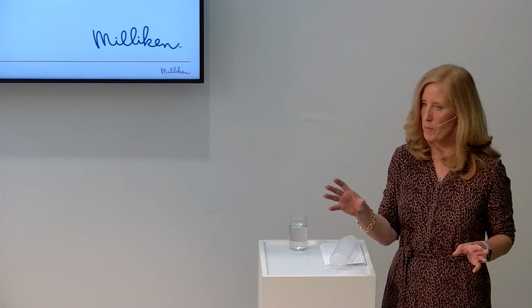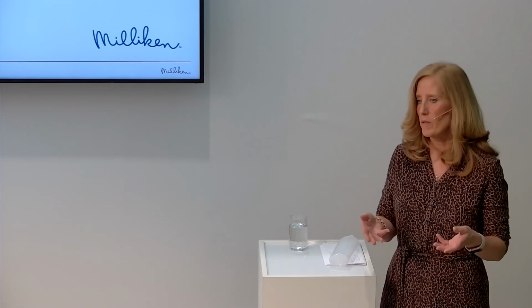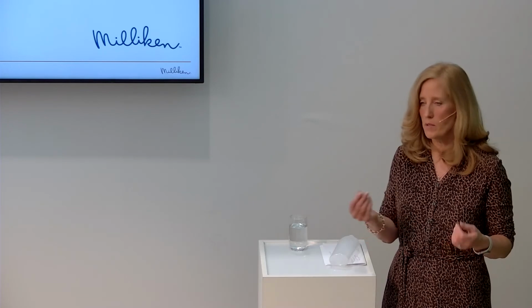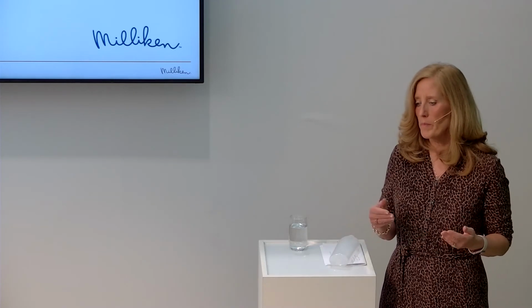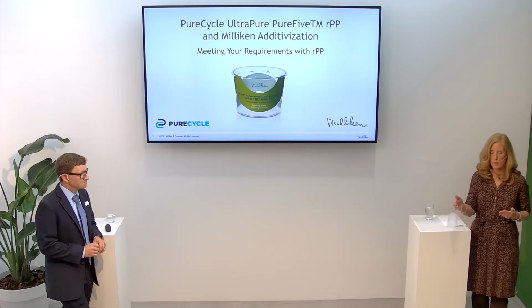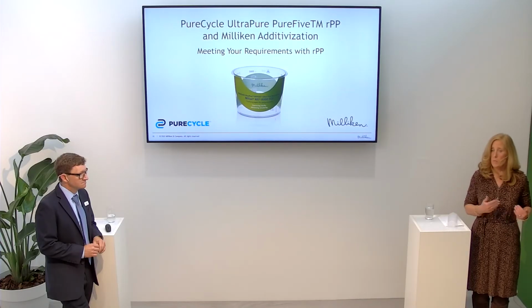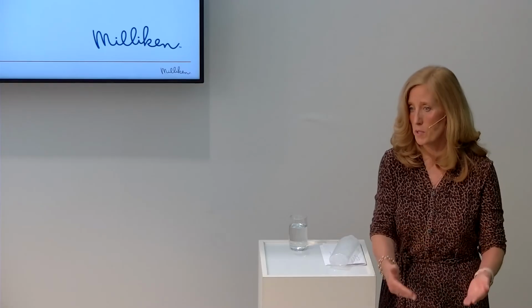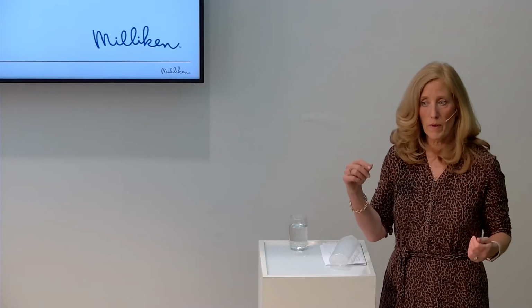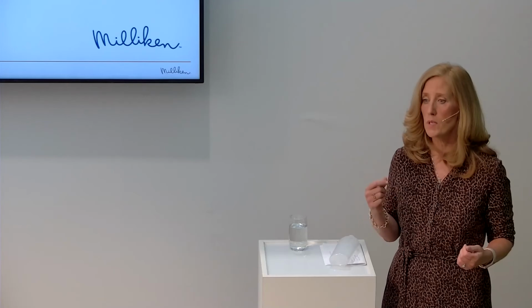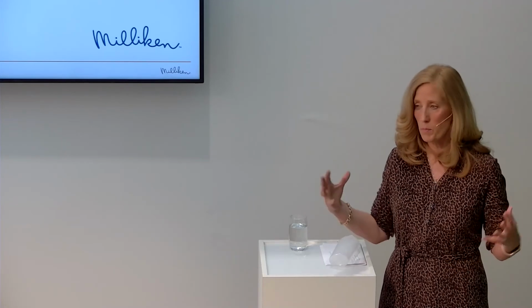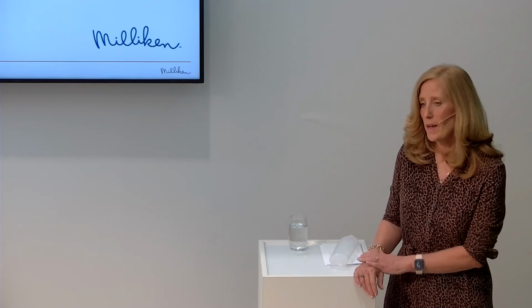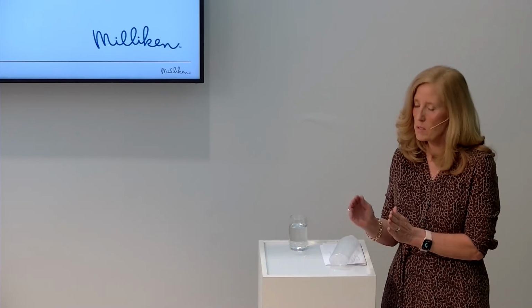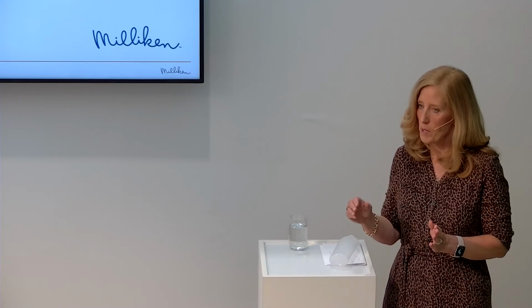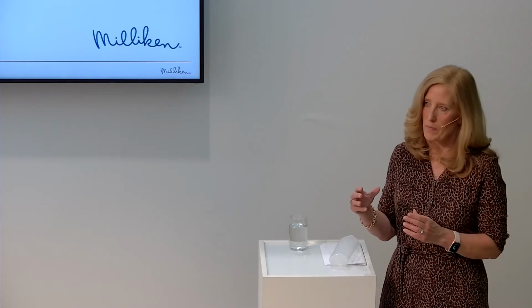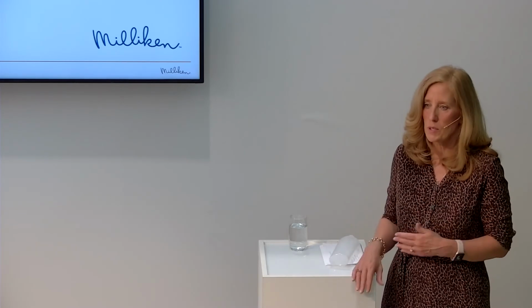You have cups that are thermoforms and cups that are injection molded, and you have thermoform trays, and then there's cutlery. In order to be a partner with a major sports team, we've said the way to make it economical to recycle is to become a monomaterial serviceware supplier. So we've got injection molded cutlery, thermoformed cups, and injection molded cups. Blended together is very similar to curbside. And curbside tends to run just a little bit lower, like 8 to 15 melt. So you can see that we still can hit the 15 melt flow as a consistent material with blending.